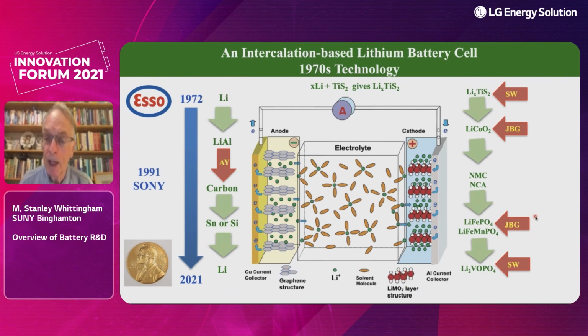John also came up with the idea of using the olivine lithium iron phosphate, much lower cost, safer, but much lower energy density, and I'll show you a few numbers in a moment. One way of increasing the energy density is to switch iron out for manganese, increasing the voltage from 3.5 to 4 volts. That gains you a bit. But if you could really intercalate 2 lithium ions or 2 sodium ions in these phosphate lattices, you could get almost back to the energy densities of the layered oxides. I don't think I need to go through this picture for the present audience.